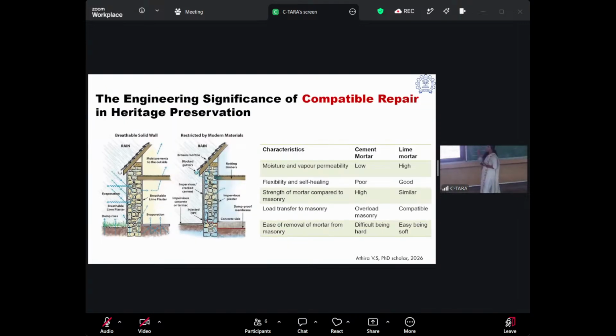Now I'm coming back to the story which I was telling a while before. Here the first picture is just representative of a masonry structure. You are seeing stone inside, which is plastered by lime. When you're repairing it, if you are using cement for plastering, initially, inherently, it was a breathable structure. So vapor was continuously moving in and out, water might move in and out, and that is okay for these structures which are more porous.